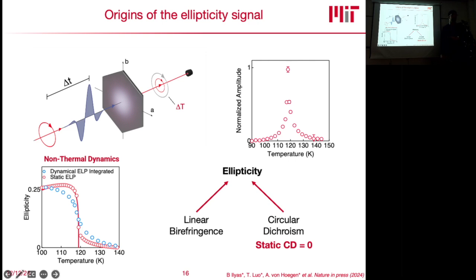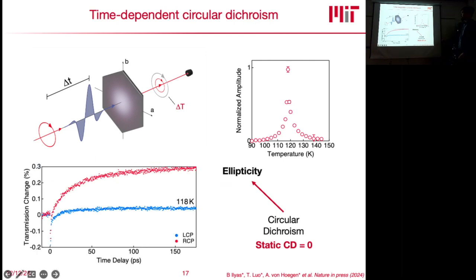And this is also something that we measured and confirmed, that there is no circular dichroism in this material, as you would expect for an antiferromagnet. However, what we then did is send in circularly polarized light, left and right, and look at the transient change of the transmission of left and right circular polarized light, which is the definition of circular dichroism. And so this is what we found.